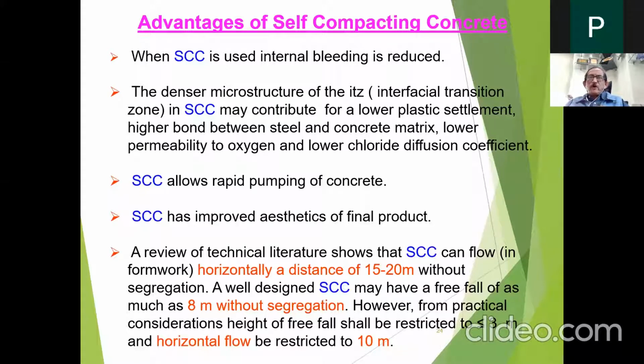So even if you have the oxygen permeability test, which is coming in IS 456 as a revision, an amendment, then there also you will find that if you do SCC, it will have a lower oxygen permeability. In RCPT also, or chloride migration, as per Nordtest 492, it would be showing better results. Then SCC allows rapid pumping, as I have told you. SCC has improved aesthetics of finished product.